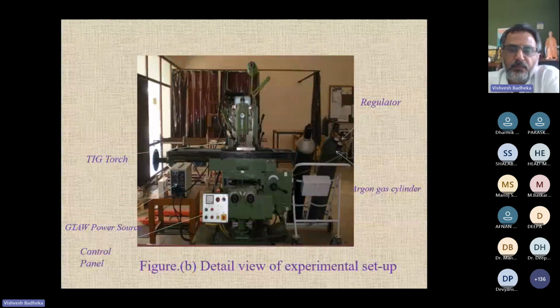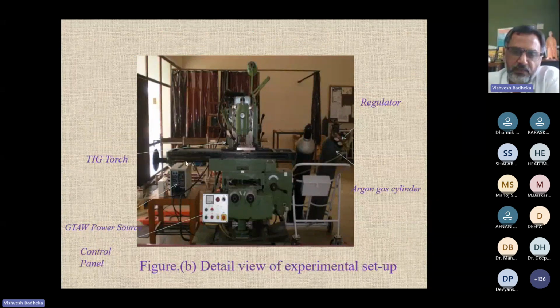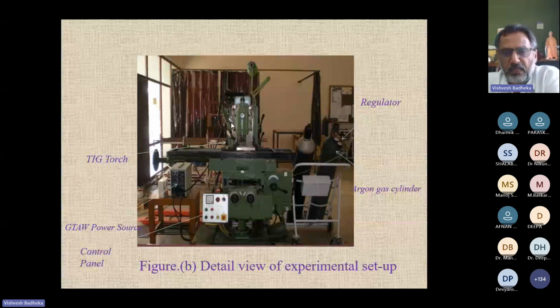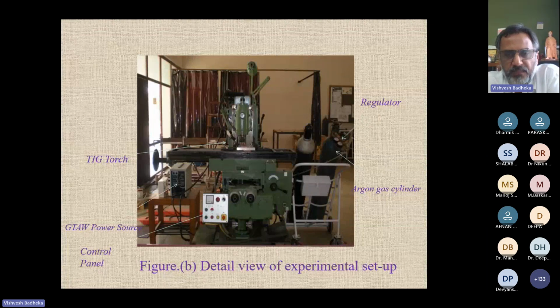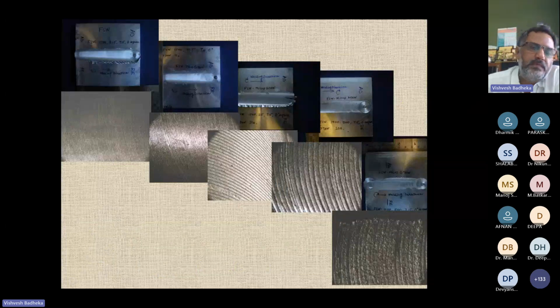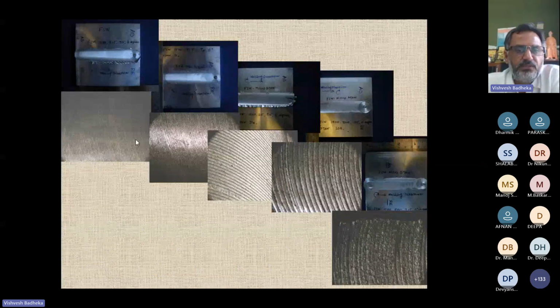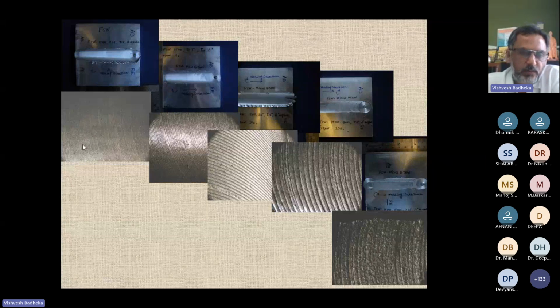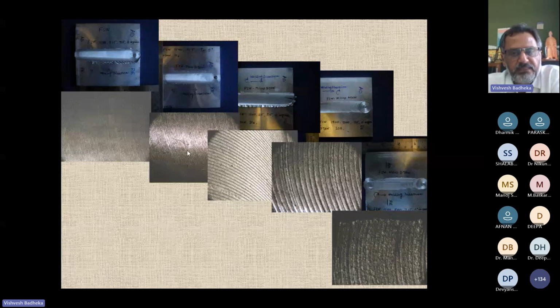And this is the complete setup, wherein you have a vertical milling machine which has been clubbed with the gas tungsten arc welding torch, because shielding gas is also required. Experiments were performed with assisted heating mode with the GTAW, because tungsten is a non-consumable electrode and the arc is not going to interfere while working with FSW. You can see here very fine rings. This onion ring, what you're observing, is very difficult to distinguish at this particular parameter. But as your welding speed increases, you are able to distinguish the onion ring, and you are able to measure it also.